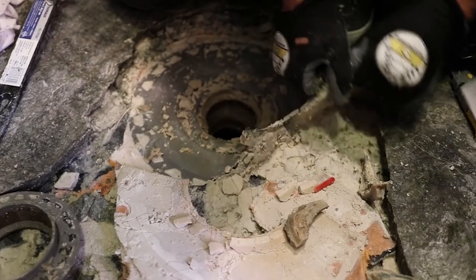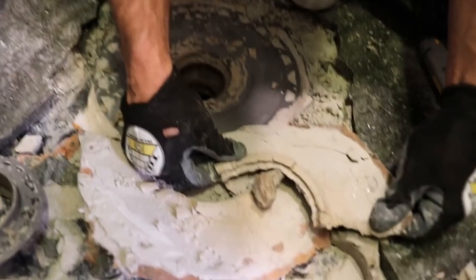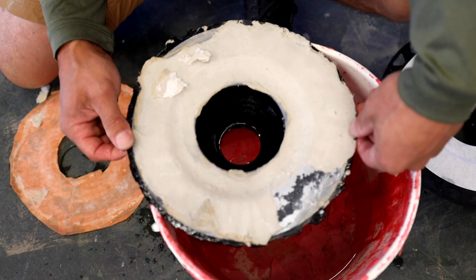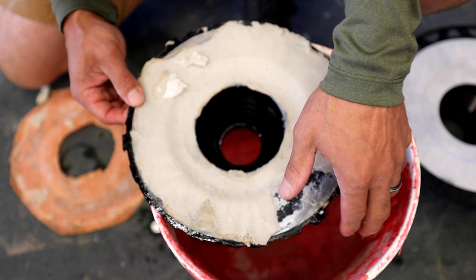The whole thing was just this black that showed. So basically, this whole fleece just disintegrated or whatever with time under water. And the water had gone up under the fleece and got the mortar bed saturated.